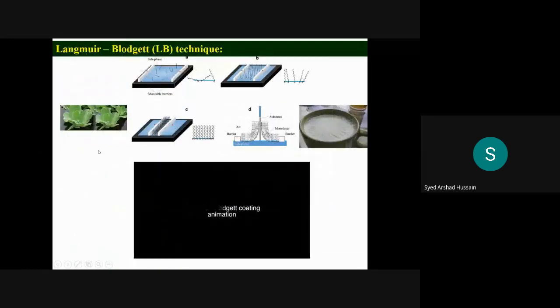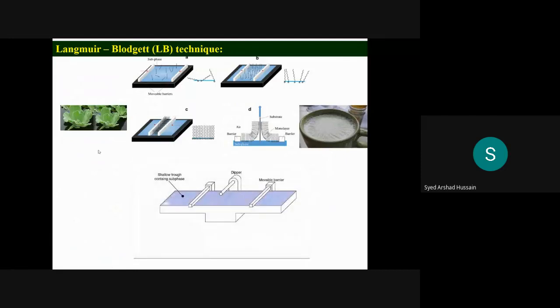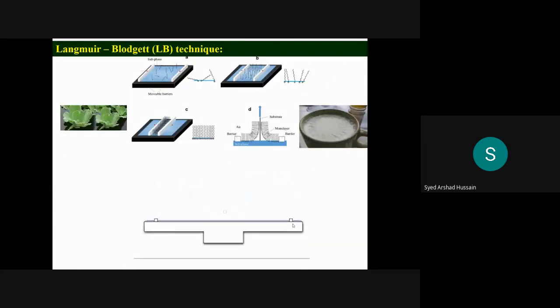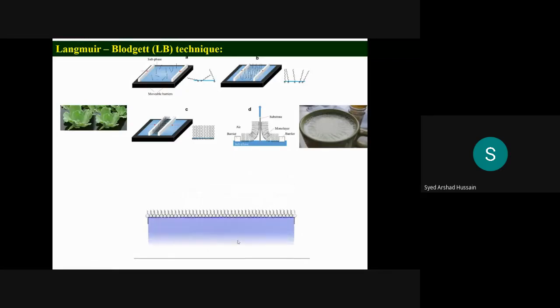Here I just demonstrate how we prepare a film using LB. So this is the trough where you spread the molecules, and this is, you know, like a water plant floating on the surface. What we do, we make a dilute solution using chloroform or another volatile solvent, then we spread it, and it's like this water plant. Then we compress using this computer-controlled barrier, so the molecules come close to each other. Then we deposit this film onto a solid substrate for study or application, whatever it may be.